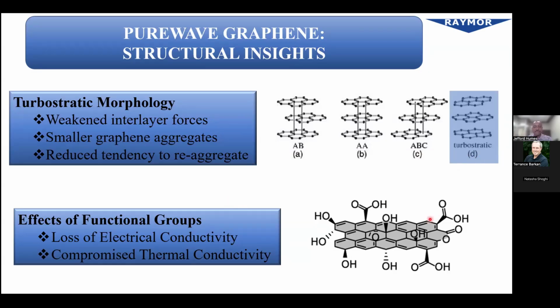One of the things that I will be transparent and kind of warn about is that it is best to use our material in its raw form, but functional groups can be added. But we have found that adding functional groups does cause sp2 to sp3 hybridization, which might reduce electrical conductivity and may also compromise thermal conductivity by creating defects in the lattice structure. But still, this has been done effectively. I just wanted to be transparent and talk about that property.